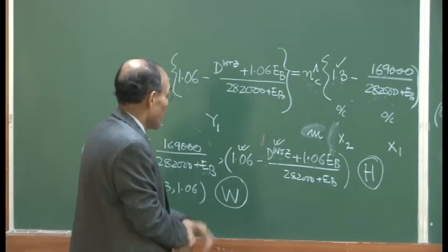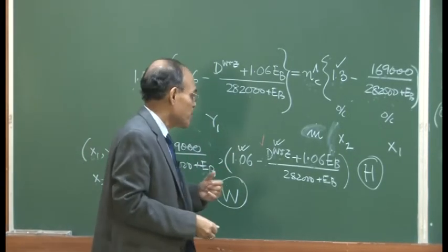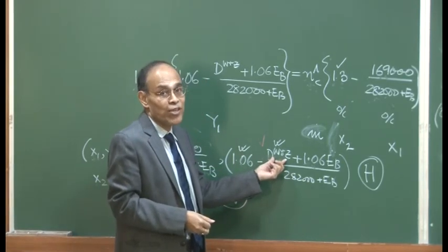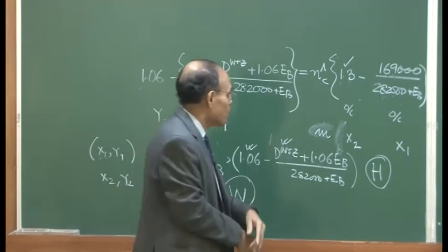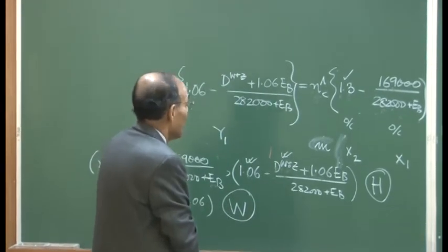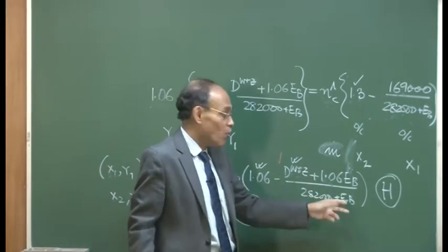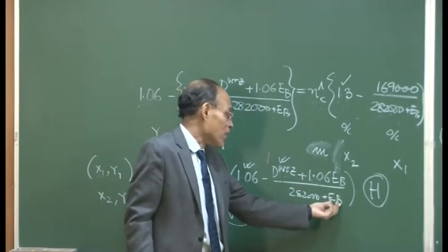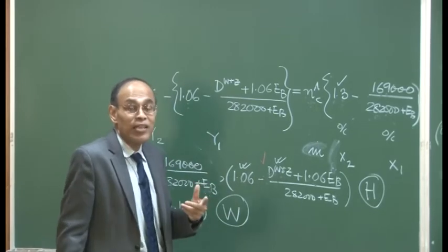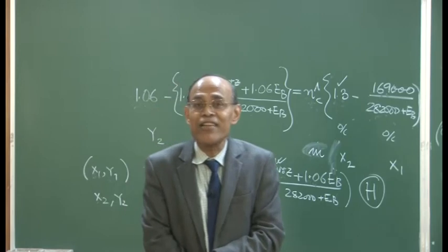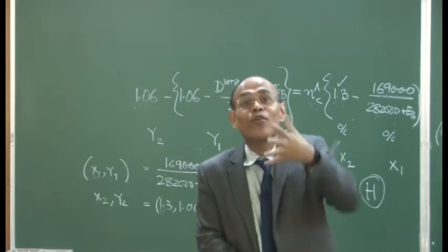with regard to, for example, if you have oxygen enrichment, actually you will have lesser volume of nitrogen going out and more volume of carbon monoxide and carbon dioxide. So, the dWRZ term is going to be also changed. And if you remember, you have enthalpy of the blast. Okay? The enthalpy of the blast term contains what? It contains the 0.79 by 0.21 factor. So, if you have 2% oxygen enrichment, it is going to be now 77/23.